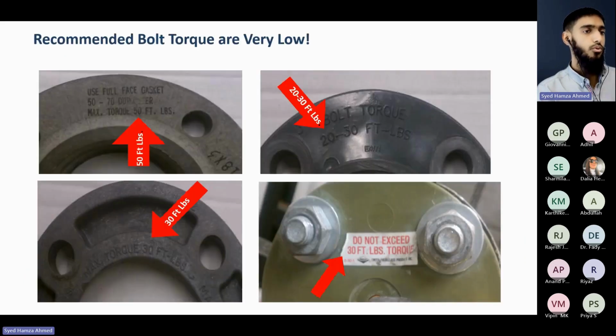Again, talking about the bolt loads that are available, we have extremely low bolt loads available. As you can see, in multiple examples we have about 50 foot-pounds of torque, a maximum torque value that is recommended for this kind of flange. Somewhere around 20 to 30 foot-pounds of torque value is given. 30 foot-pounds, as we can see in this glass reinforced epoxy flange. So we have very low bolt torques. A common aramid gasket, for example, requires at least 120 foot-pounds of torque, generally speaking, in these types of similar flanges of similar size. So compared with FRP and GRE flanges, this is extremely low.